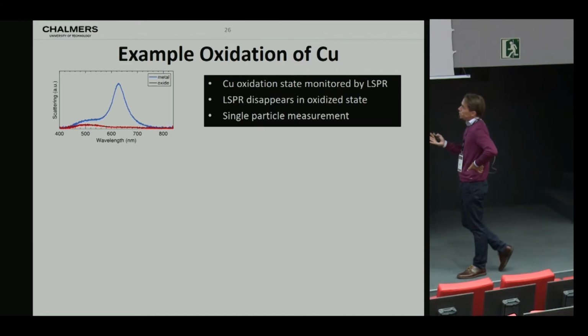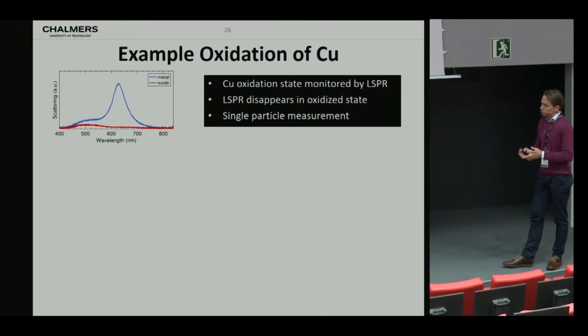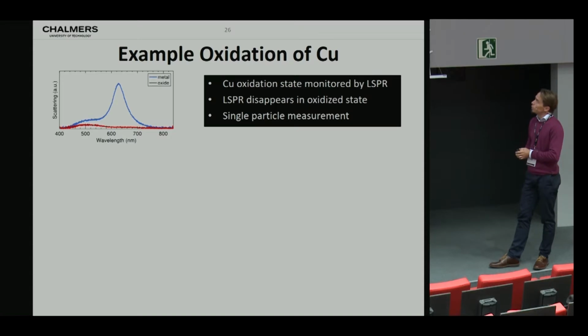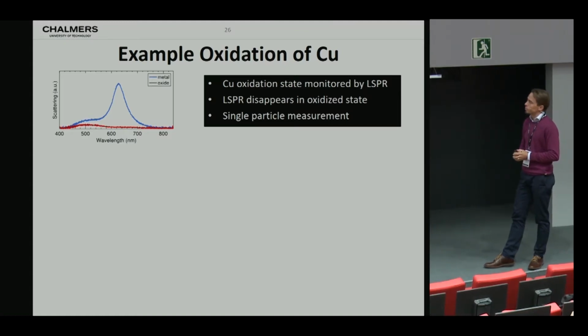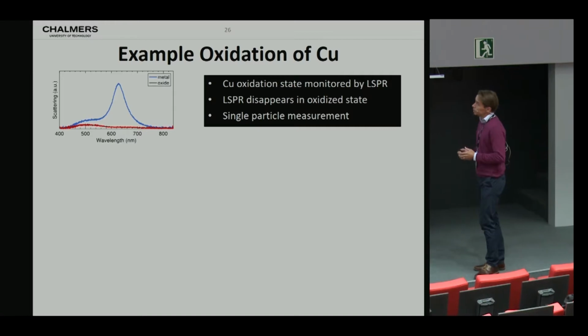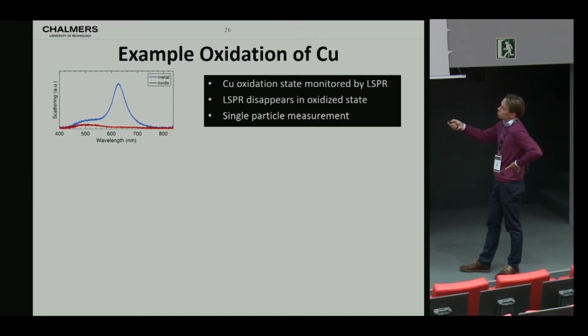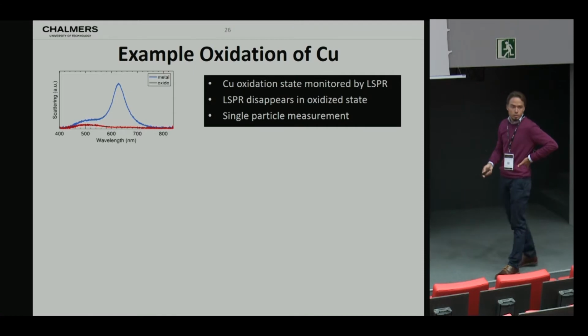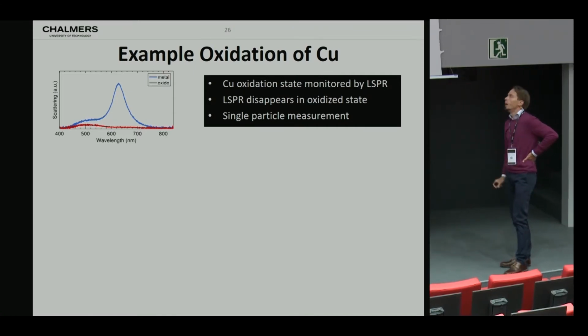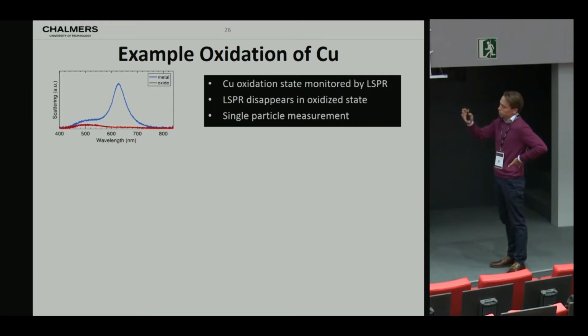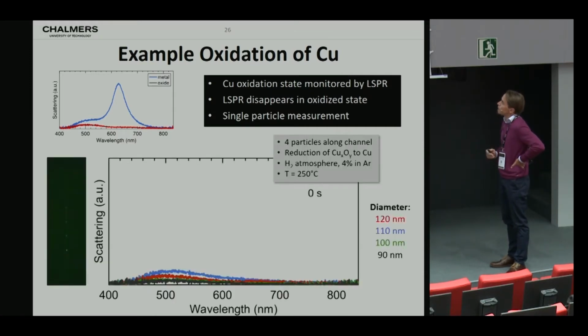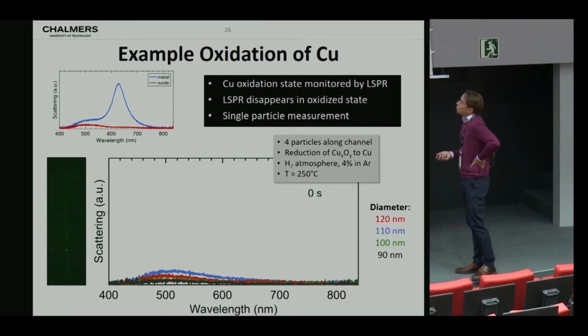So let's now see what this can do for us, and I'd like to explain this with the first quite simple example on the oxidation of copper nanoparticles. Why copper? Well, copper is an interesting material as it catalyzes a number of very interesting reactions. And it is also nice in the sense that as copper is metallic, it has a strong plasmonic resonance with a distinct scattering peak, but as it transforms into an oxide, you basically lose that signature completely. So you have a very strong optical signature for the transition between the oxidized and the reduced state. And then to start with, you can do the following experiment.